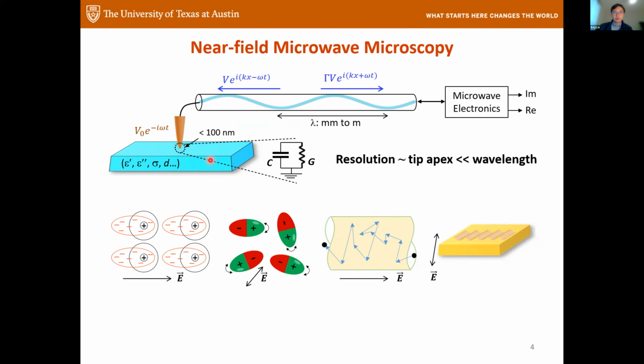So for those of you who are doing transport, you know a mega ohm per square is very insulating for a lot of the quantum system, right? Because the quantum resistance is 25.8 kilo ohm per square. So in other words, we are fairly sensitive in the insulating part, but once the material gets a little bit conductive, we start to lose the sensitivity. And this is one of the reasons that I feel a little bit puzzled by the data we took, which I'll tell you later.